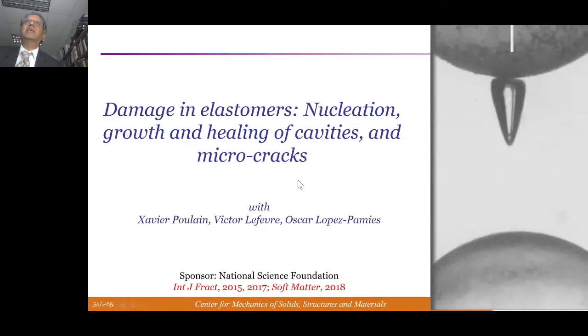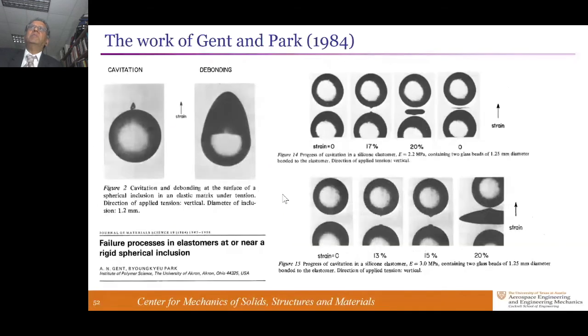It's a recreation of something that Gent worked on starting in the 1950s in PDMS specimens. This is a PDMS that has a glass bead embedded inside of it. If you made the specimen badly, poorly, the bead will separate from the PDMS and you'll see a debonding, and that's not a desirable thing. So you go through special processes of tailoring the surface so that you have a very strong interface and there's no interfacial debonding. Then cavities pop in the bulk, and this is an important nucleation problem because this is the starting of failure in these materials.